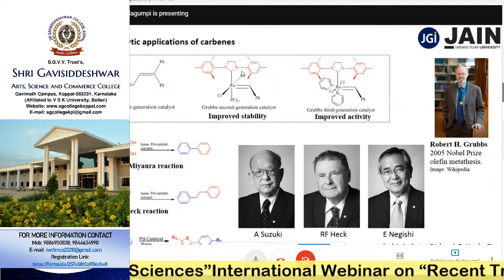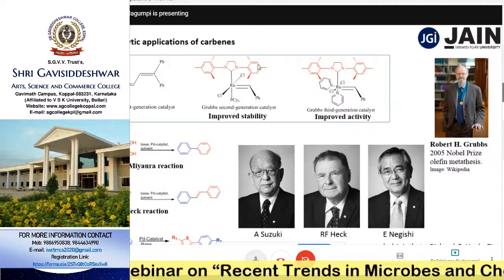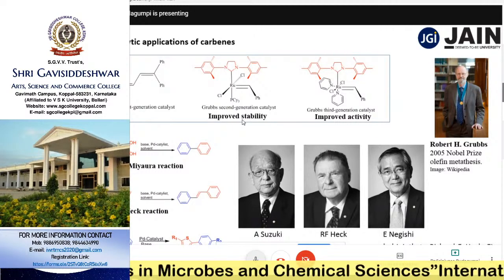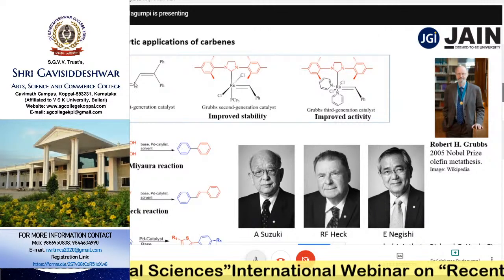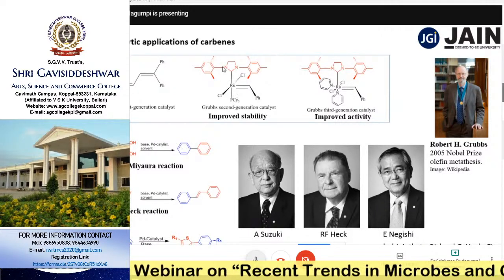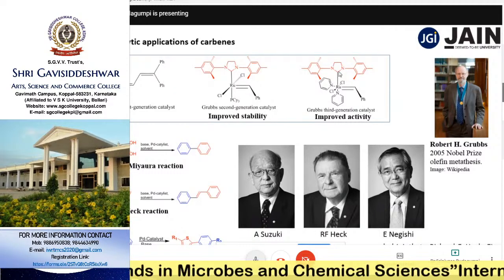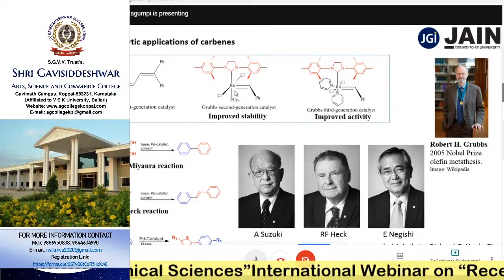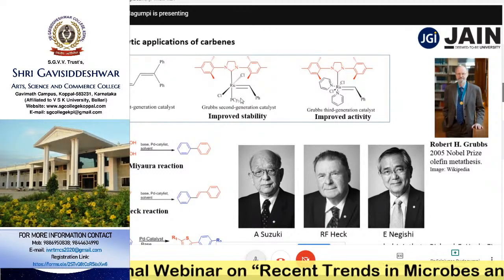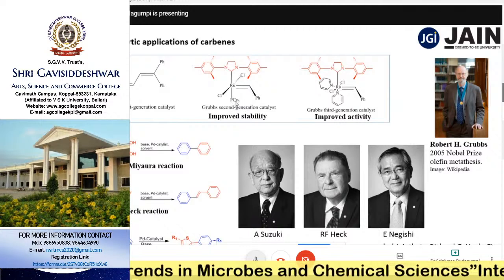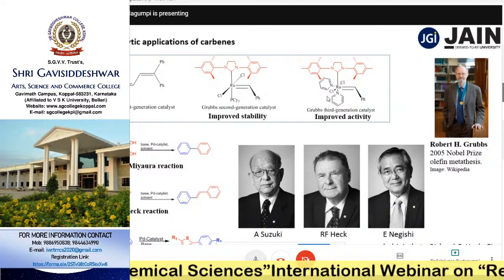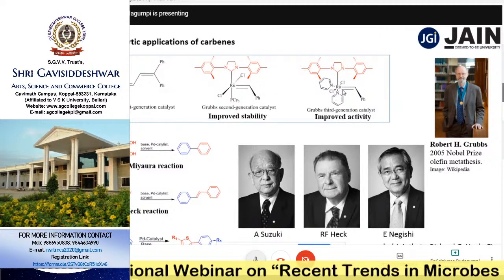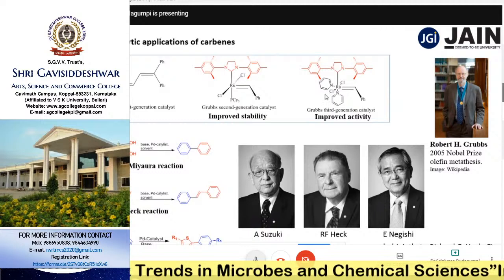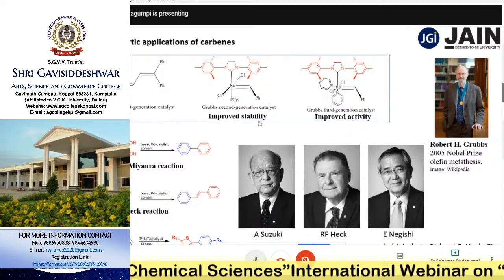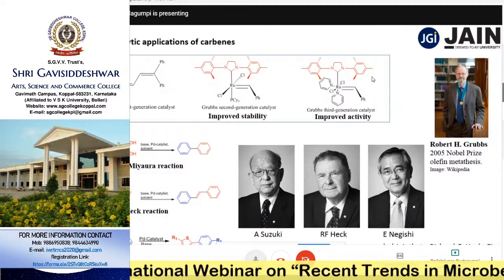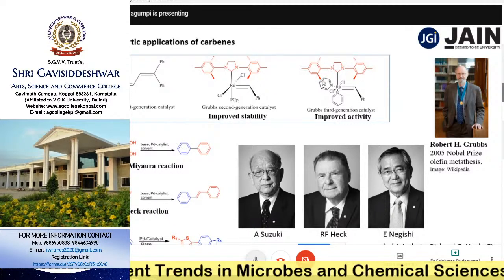This is an imidazoline ligand, which has mesityl substitutions on either side of the nitrogens. So though this catalyst is stable for a long time during catalysis, its activity is not that improved. Activity remains the same, but stability is increased. This is considered the second generation Grubbs catalyst. In order to increase the catalytic efficiency of the ruthenium catalyst, they introduced two pyridine ligands instead of the tricyclohexyl phosphine ligand. These pyridine ligands are considered throwaway ligands, which help the ruthenium bind with the substrate easily. So this particular catalyst has given improved activity as well as improved stability, and it is still found in industries, with vast industrial application in olefin metathesis reactions.